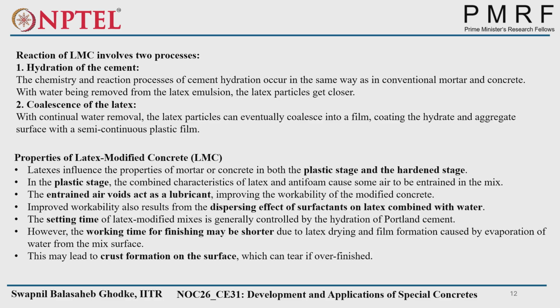Plastic stage means you are in the initial hardening or initial setting stage, or a couple of minutes after that also. In the plastic stage, the combined characteristic of the latex and antifoam causes some air to be entrained in the mix. That air will be helpful as a lubricant, and because of that lubricant we have higher flowability. We are already reducing the water, so we want to maintain the flowability. That flowability is maintained by these entrained air voids.